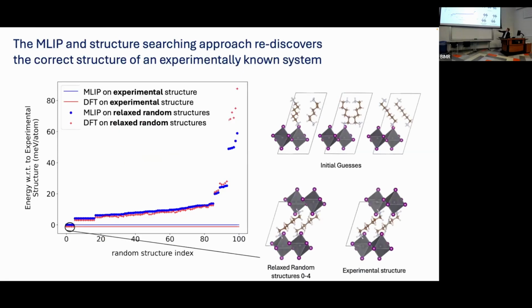evaluate. Here, what I'm showing is the relative energy to the experiment. We knew in this case what the experimental result was as a sanity check, and that's this line. So this is DFT on the experiment, then the MLIP on the experiment. There's some error between the two because the MLIP model has been trained on DFT, but it has some error. And these are all the trial structures. Eventually we start from some pretty bad guesses. These are the initial guesses. They're not so good, but that's okay because we have this brute force approach. Eventually we get to something that looks very, very similar to the experimental compound.